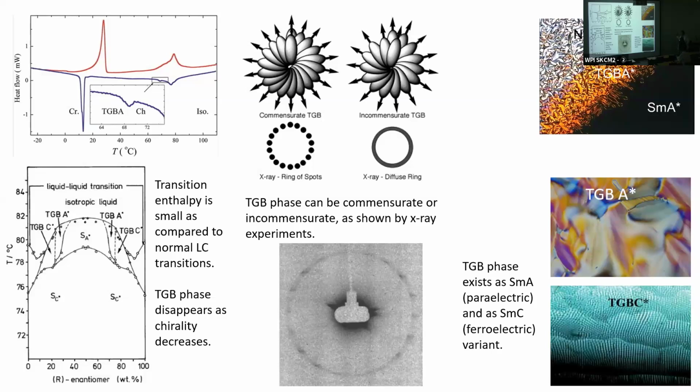If you actually zoom into this, you will see that there are equidistant patterns of lines as well. So there is actually a helical structure. And then you have the cholesteric phase up here. There's a clear difference in birefringence. So they really do exist, but over very small temperature ranges again.